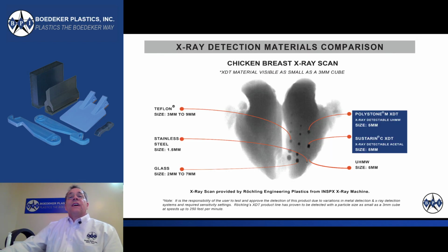Okay, in this case, you can see that we put the contaminants inside of a chicken breast, and you can see visually the level of detectability. So again, we're talking about contrast in densities here. The X-ray detection equipment is heavily related to density. So let's start with stainless steel. If we look at the stainless steel contaminant, here's a 1.5 millimeter sphere, and it's very small, yet very clear and very easy to see. So that would definitely be detected by the X-ray equipment.